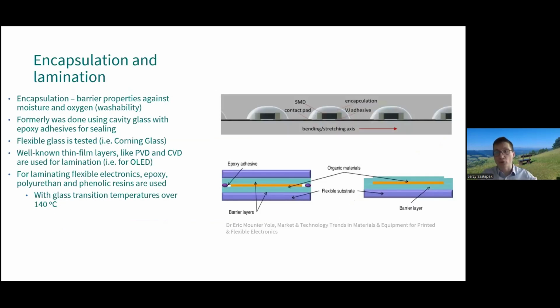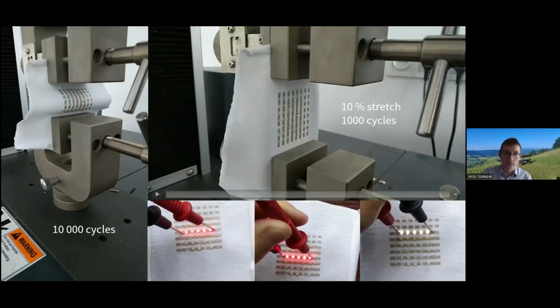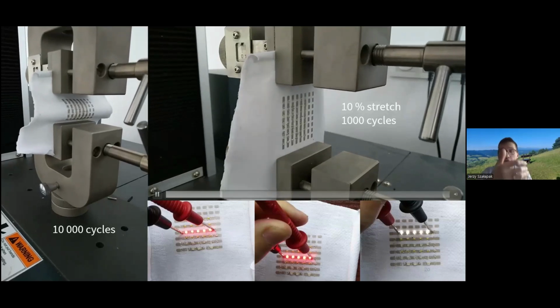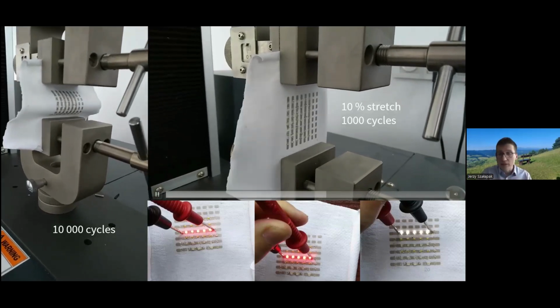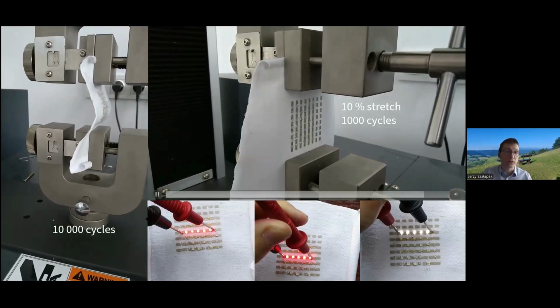To improve mechanical properties and additionally create a barrier against moisture and oxygen, lamination or encapsulation may be used. Lamination requires higher temperatures and additional pressure, which is too much for some materials, especially stretchable ones. We used encapsulation, which is basically a polymer glob top, so a polymer droplet placed on top of a chip. It allowed us to double the mechanical parameters. Encapsulation polymer needs to be stretchable as well if we are aiming for stretchable substrates, so only certain types of materials may be considered. And so our joints were tested mechanically for bending and stretching for 10 and 20%. And the resistance rise of the samples never exceeded 20%.